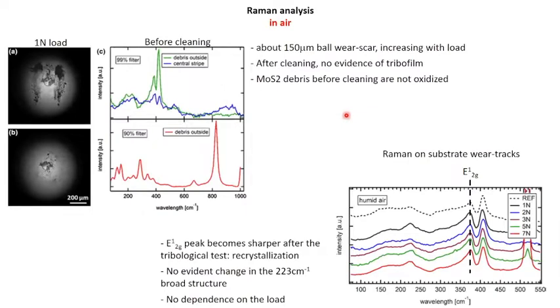And again, still using the Raman analysis, we want to deepen the aspects related to the measurement in air with respect to the measurement in vacuum. Here I reported the images that you have already seen related to the measurement in air at 1 Newton load, where you can see the presence of the debris. These debris really do not adhere to the substrate, because by gently cleaning the surface, you can see the complete removal of this debris.